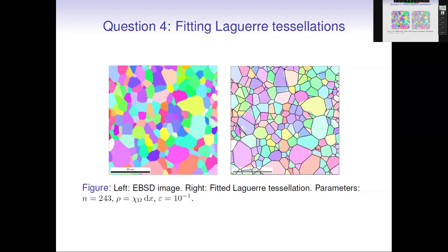It seems that everything's very nice, highly uniform, and this is a nice example of that. The grains are quite similar in size. That needn't be the case, especially if you look at multi-phase steels, like dual-phase steels, let's say made of ferrite and martensite, where the martensite grains could have a diameter that's maybe 10 or 20 times smaller. So the optimal transport will let you control the volumes fine. It's true here that it's a nice example.